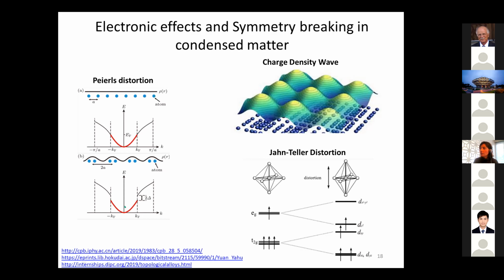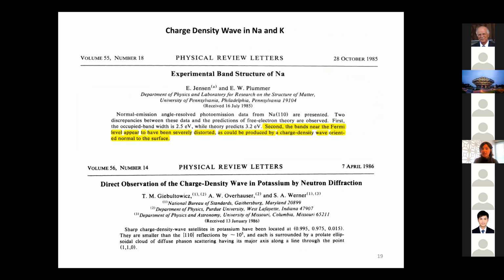In fact, from the simplest of elements, the alkali metals, we start seeing these effects. For example, both sodium and potassium are known to have shown a charge density wave, and this has been known for a while, but there are more recent studies that have confirmed this possible presence of a charge density wave in alkalis. This is as a function of temperature. You cool them down and they do this charge density wave.